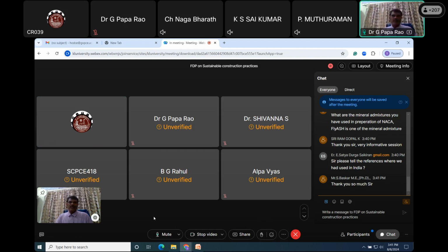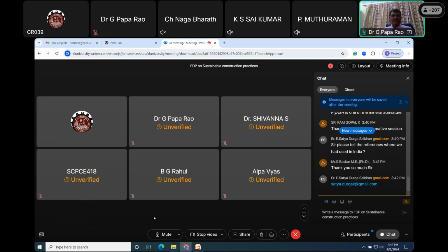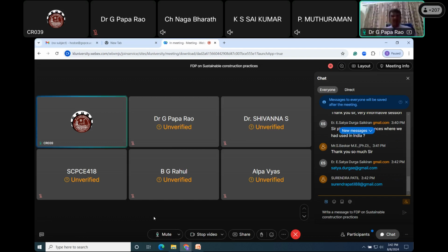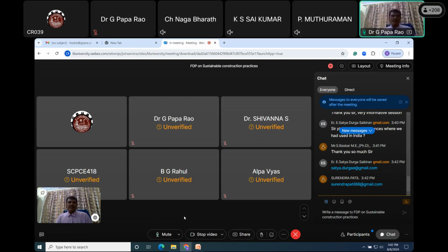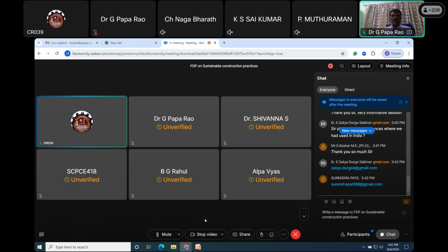As I already told you, we have constructed a two-storied office building for NTPC using 100% fly ash aggregate. We have not used any natural coarse aggregate. The entire coarse aggregate was replaced with our fly ash aggregate only. It was constructed 4 to 5 years back, and still it is functioning well. We have not observed any cracks so far. I will share that paper. We have published one paper in a conference on the two-storied office building we constructed.